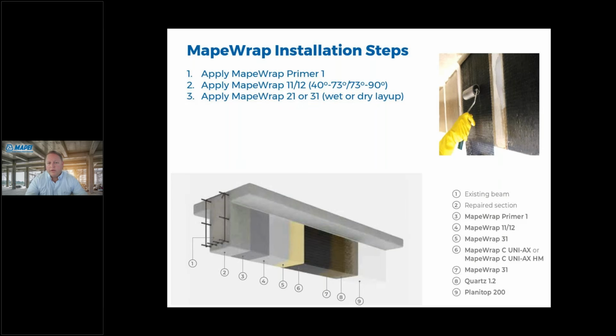And then we have 2 resin systems formulated for if you want to do a wet layup, which is where you are going to be saturating the fibers before you put it onto the concrete. This can be done with a saturating machine where the fibers will roll through a machine. There's a resin bath. It will get it all wet with resin, and it'll squeeze out any excess, and then you roll it onto a PVC tube and take it over to where you need to install it.